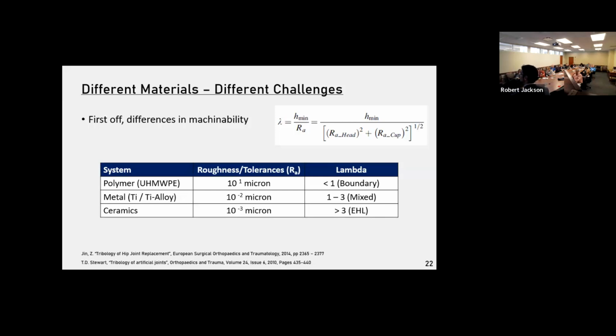Alloys also aren't perfect. They can be machined to tighter tolerances. So we're operating now in that 1 to 3 lambda, the mixed lubrication, getting to lower friction. But you have problems with biocompatibility. Titanium might be compounded with things like chromium, molybdenum, and you don't want heavy metals like those to leach out. So there are problems with these magic alloys that certain shows profess are the answer to everything. And ceramics can be polished down to an order of magnitude finer, so 10 to the -3 microns. And you're talking the EHL, elastohydrodynamic lubrication regime. Very low friction, but you have problems with a very tough, rigid ceramic that doesn't quite mesh with the modulus or the toughness of the surrounding tissues. So even though something's a composite or an alloy, that doesn't make it special. It doesn't really overcome the vulnerabilities or the inherent drawbacks to some of these.